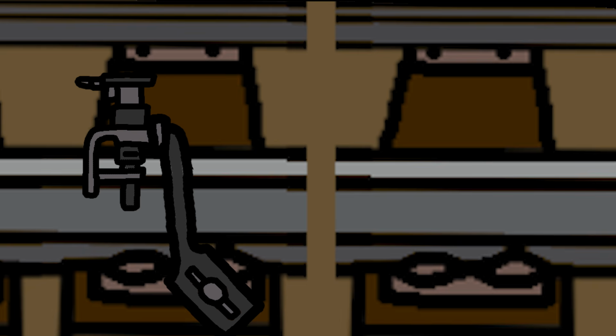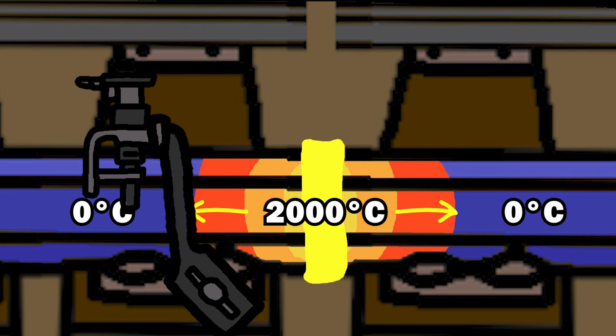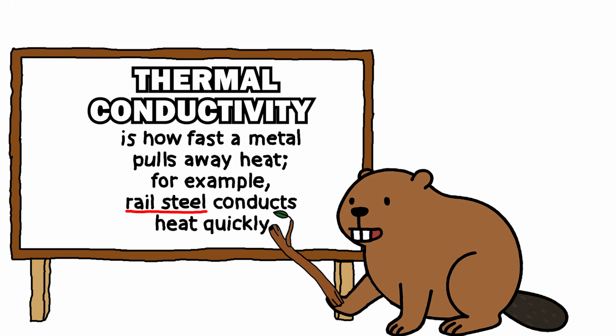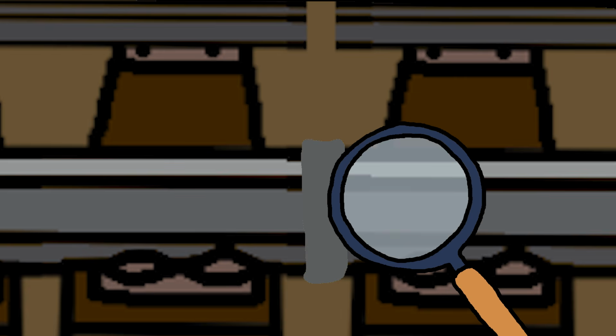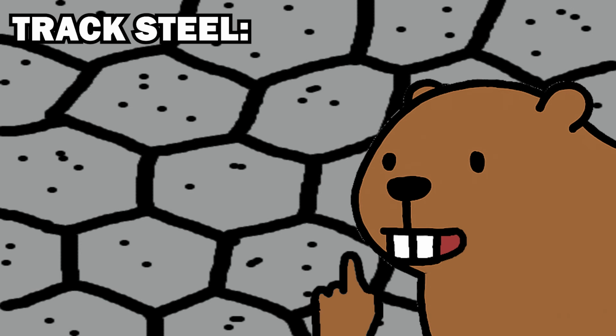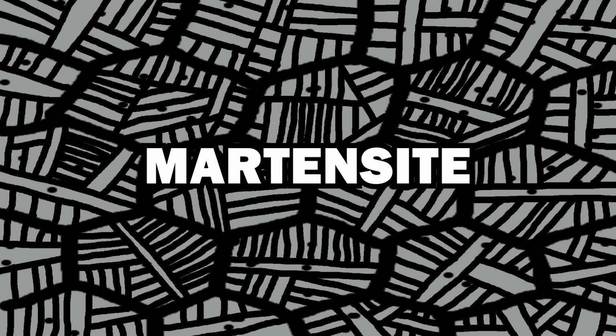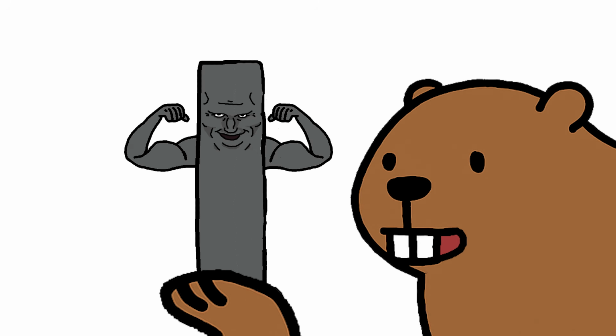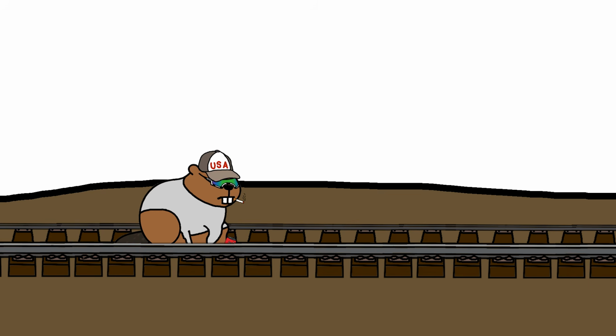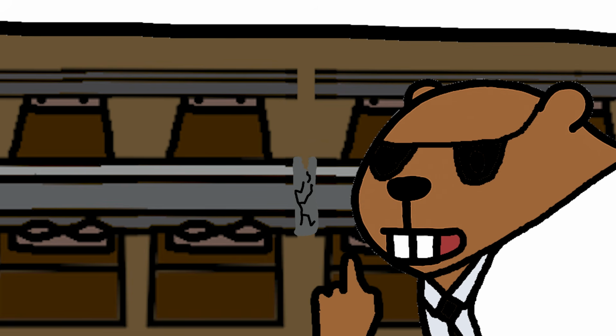Without preheating, the weld will cool rapidly, as the heat gets drawn away, since the temperature of the tracks is colder than the weld. This effect directly ties to thermal conductivity, creating problems like brittle cracking in the heat-affected zone, as the rapid cooling traps the carbon grains, forming a needle-like microstructure called martensite, which is extremely hard but very brittle. If a heavy weight, like a train, were to roll across it, scientifically, it would break in a brittle manner,